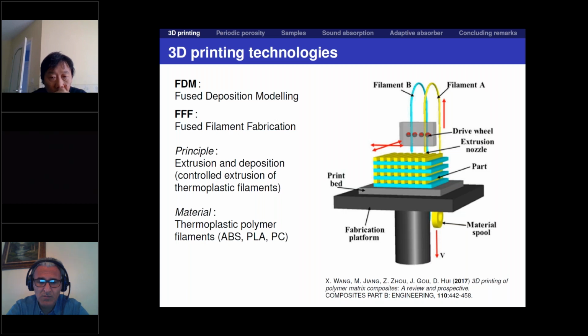The first one is the so-called fused deposition modeling or fused filament fabrication. There are usually more than one name for these recently developed technologies. And here you may see a picture which illustrates the principle, which is some kind of controlled extrusion and deposition of thermoplastic polymer filaments. The filaments are provided in spools. So here you have a spool of the material, and it is driven using, let's say, two gear wheels into a header, into a nozzle, which is heated up to a certain temperature. And at this temperature, the polymer melts down to a liquid state.